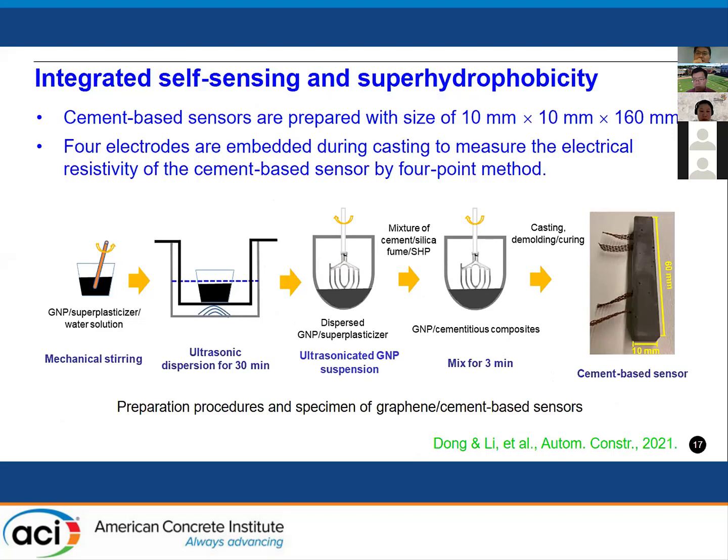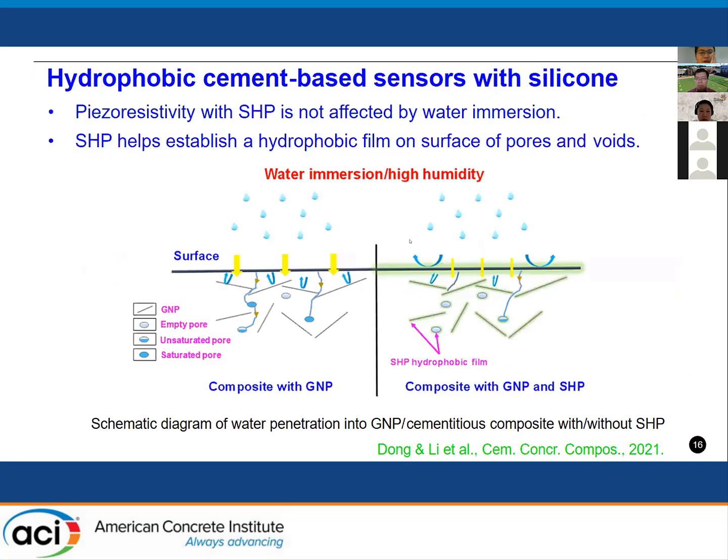So I have a follow-up question on this one. How sensitive was the resistivity measurement to the ambient relative humidity? I think yes, it's sensitive to the humidity of the environment. For example, when we put the sample in dry condition and in an environment with high humidity, we can see the value changes greatly. So I think it is very sensitive.